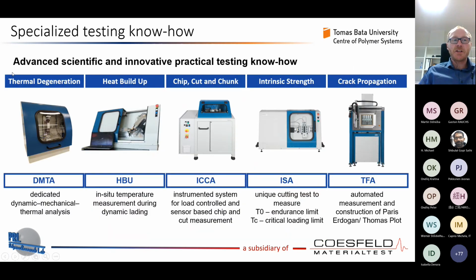Okay, I'm at the end of my presentation, and I would only like to show you special testing know-how which we have. We did a lot of developments over the last years, which I hopefully, and my colleagues in future webinars, will speak about. For example, the heat build-up analyzer, which measures heat build-up in situ under cyclic loading conditions inside the rubber sample. That's very important. And a very fresh testing method and equipment is the DMTA, a dedicated dynamic mechanical thermal analyzer, which we use for accelerated measurement of aging behavior of materials related to fracture mechanics.